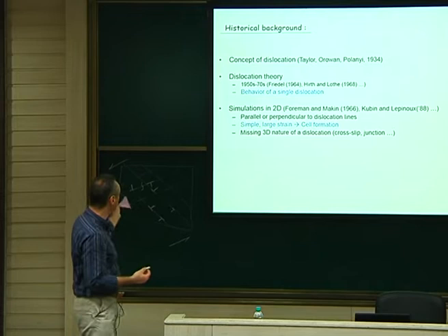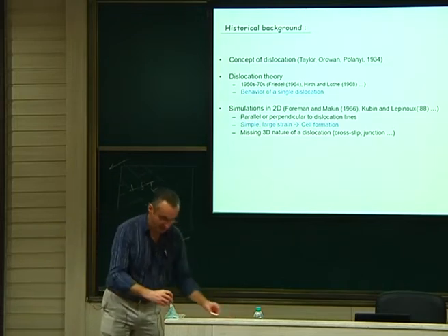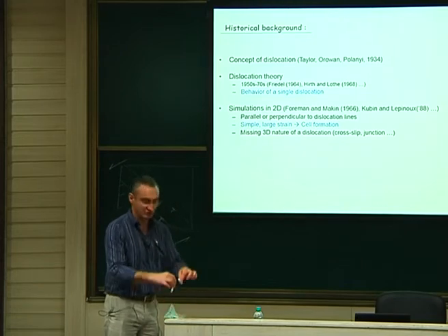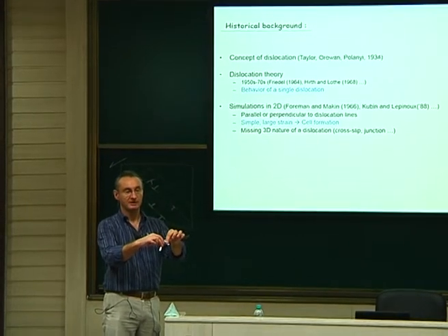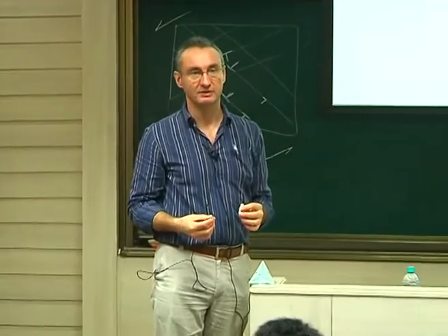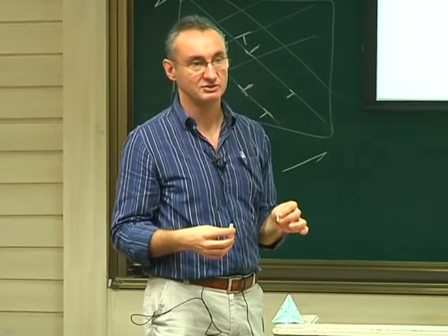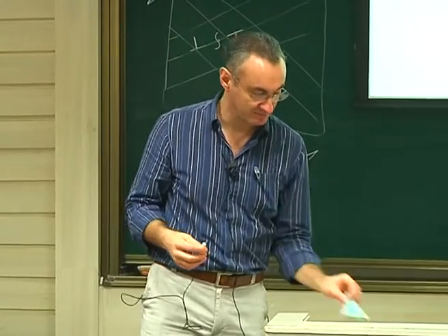So it means that when you do that, something is wrong, because in reality, if you have one edge here and one edge there, there is an angle. And here, you will assume that they are like that. And this is not good. So at least for the local interaction, this will make artifacts. So this is a problem.